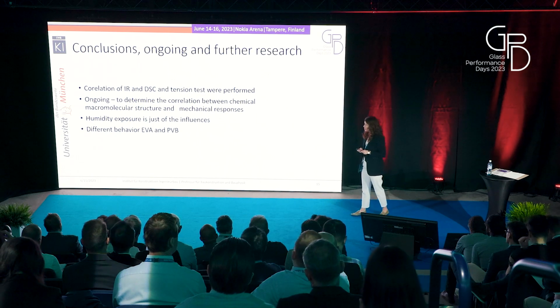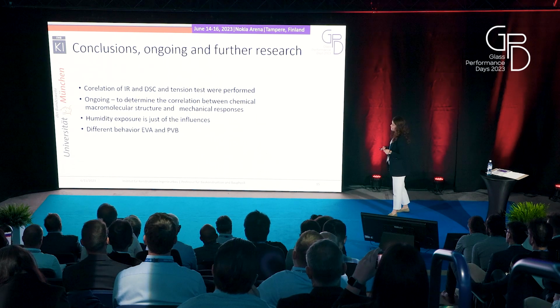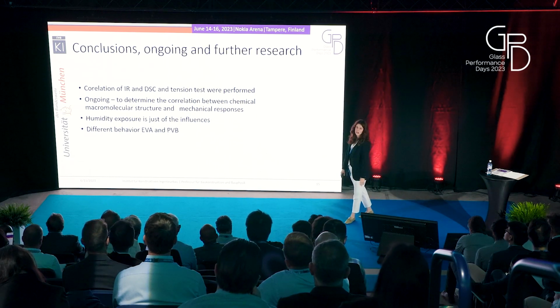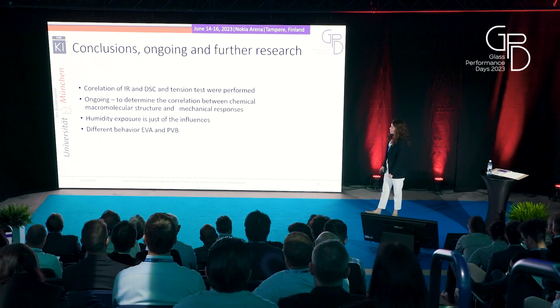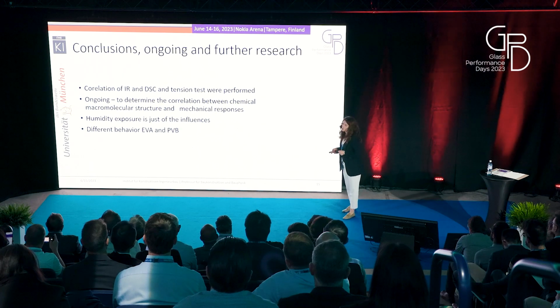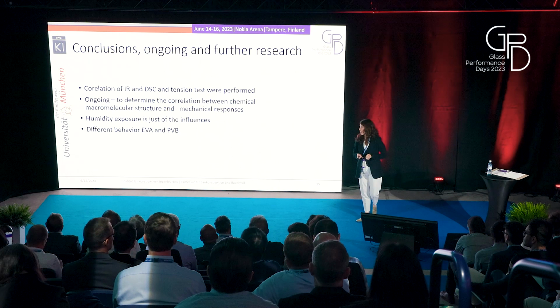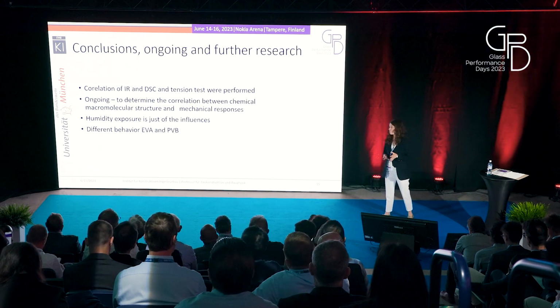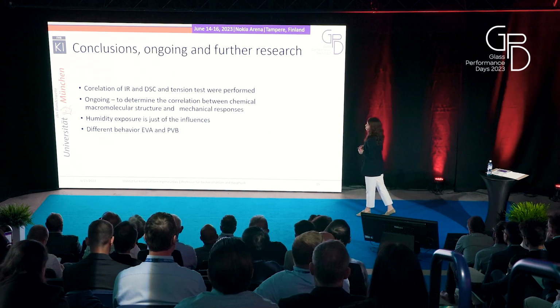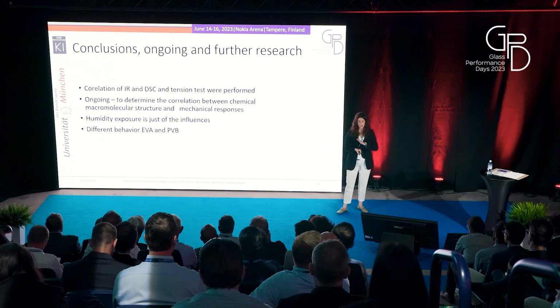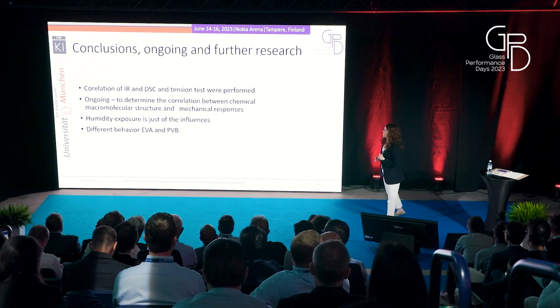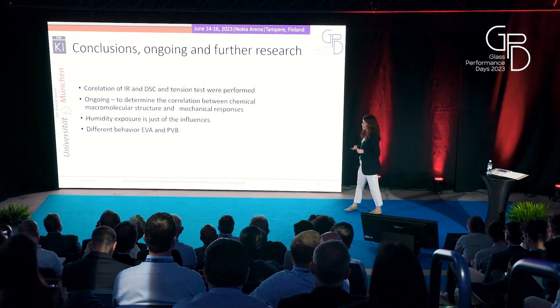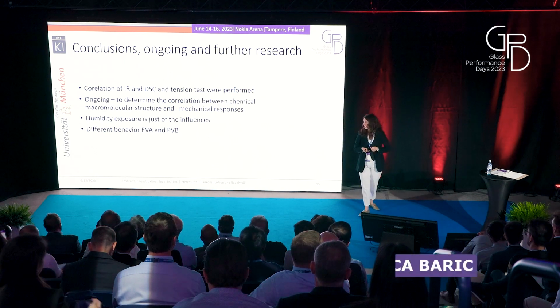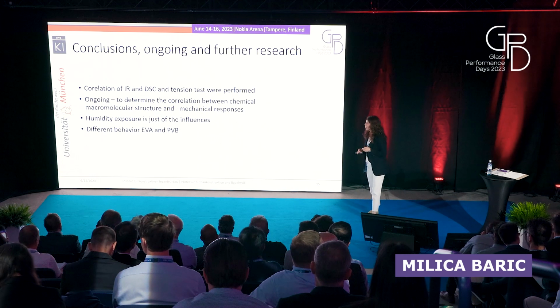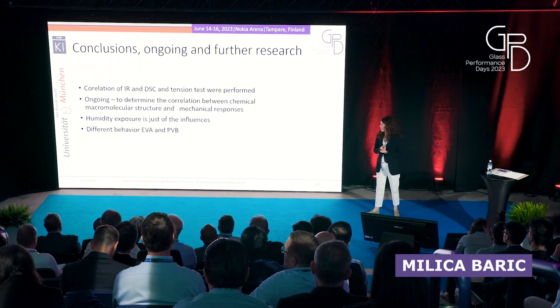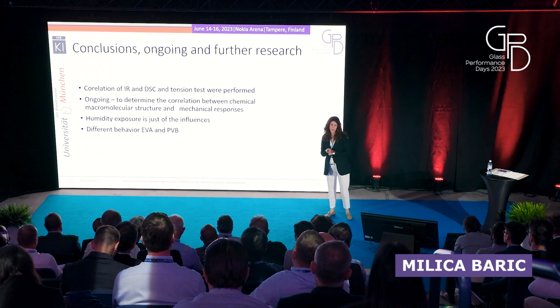So the conclusion is that we did the correlation of the infrared and differential scanning calorimetry and tension tests, so the combination of the chemical and mechanical tests. And as I said, this is just a part of our ongoing research. Our ongoing research is to determine even more precisely and in more detail the correlation between the chemical macromolecular structure and the mechanical responses. This humidity exposure is just one of them. And so far, we can see that definitely there is a different response between EVA and PVB.